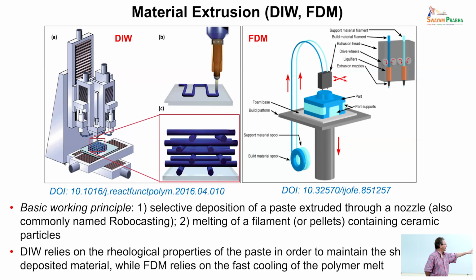One of the advantages of FFF is that it is material agnostic. What matters is the size of the powders for sintering, but you can put anything inside. So that's a great advantage. With pellets, they are easy to make. People that do injection molding use pellets. The problem with pellet printing is that it is difficult to have homogeneous flow inside the nozzle, because you have this assemblage of pellets that need to melt and create a continuous flow of molten material without voids. So the parts generated using a pellet approach typically have some internal defects, which is not desirable.